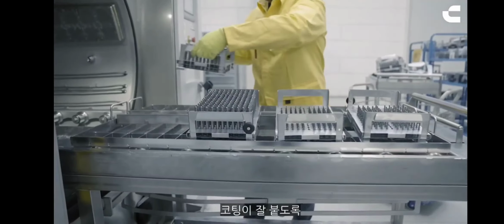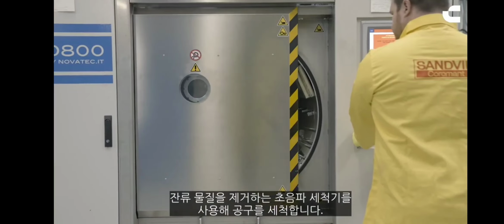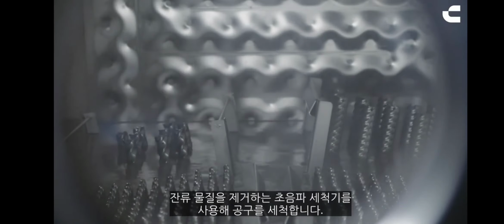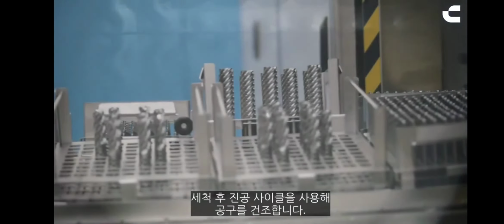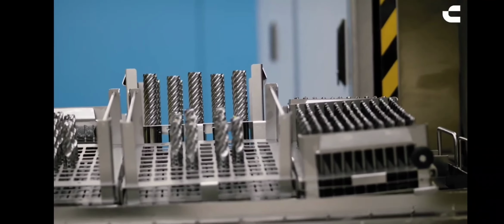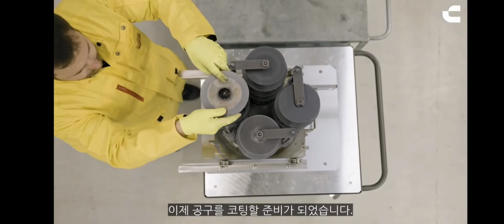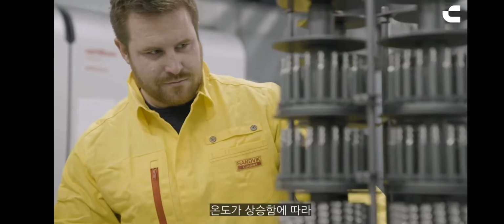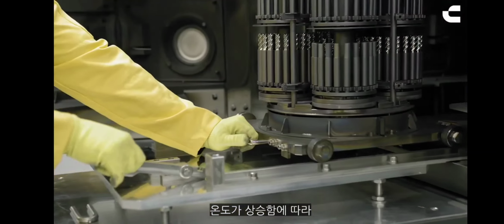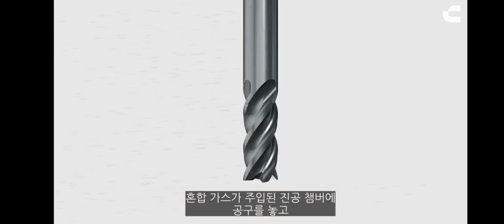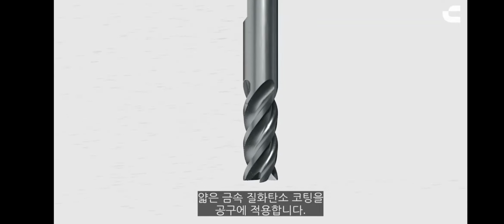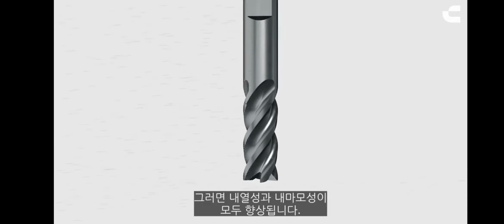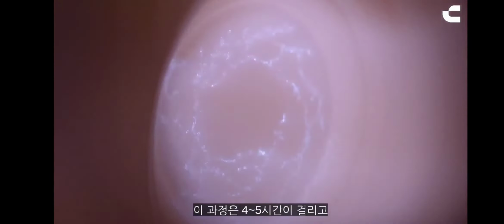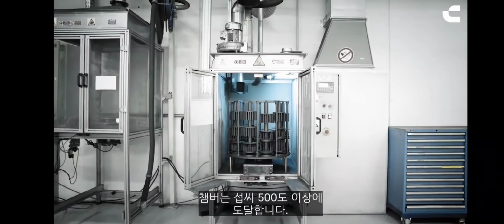To ensure proper coating adhesion, the tool is cleaned using an ultrasonic washing machine, which removes any residual material. Following cleaning, the tool is dried using a vacuum cycle. Now the tool is ready to be coated. We place it in a vacuum chamber where a mixture of gas is injected. As the temperature increases, a thin layer of metal carbon nitride coating is applied to the tool. It enhances resistance to both heat and wear. This process takes between 4 to 5 hours, and the temperature of the chamber reaches more than 500 degrees Celsius.